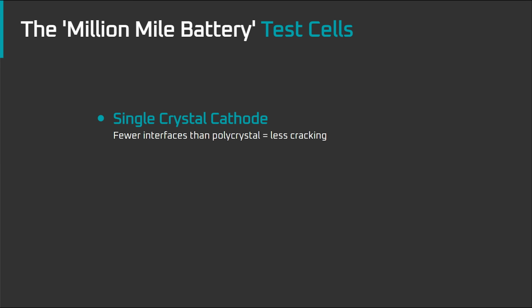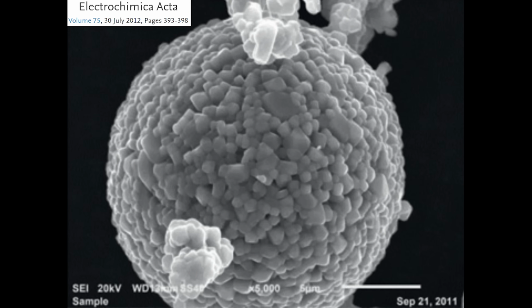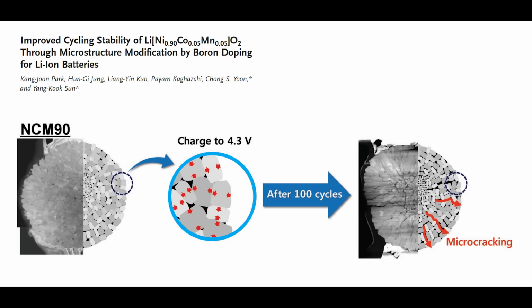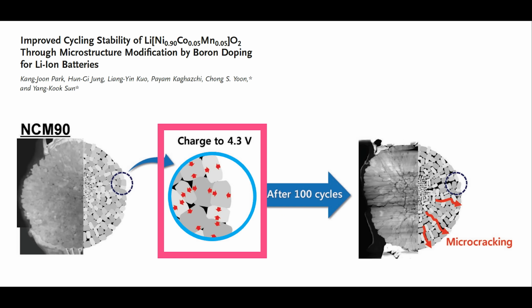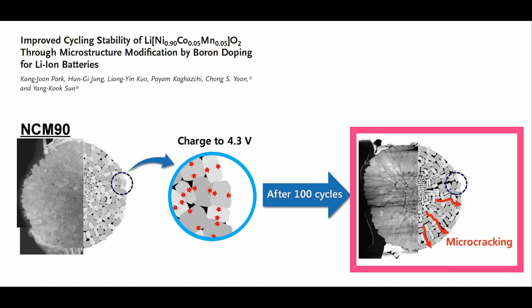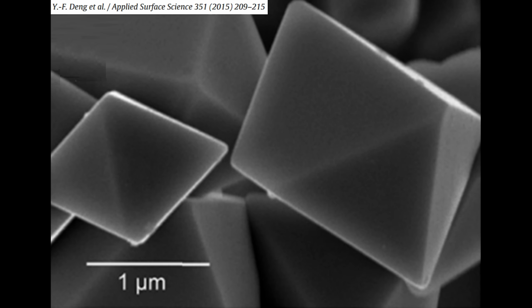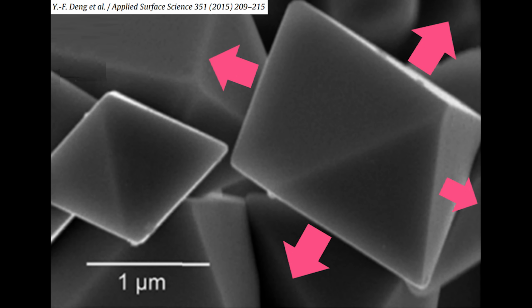The first was single crystal cathode material. Generally, lithium-ion batteries use polycrystal cathode particles, where hundreds or thousands of small primary crystals form a large secondary particle. That causes issues with cycle life because when a battery charges and discharges, the primary crystals expand and contract against each other, crack the secondary particle, and react with the electrolyte, which reduces cycle life. With a single crystal cathode particle, the crystals aren't part of a larger conglomerate and are free to expand and contract without grinding against other crystals, and therefore don't degrade as quickly.